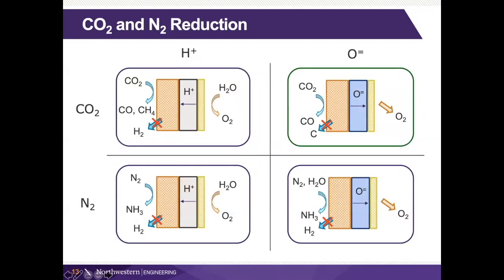And again, let me do the comparison with the oxygen ion conducting system. In the case of the proton conducting system, you bring in water, the protons come across and you react CO2. Ideally you're going to make some mixture of CO and methane. And again, we don't want to have the hydrogen evolved here. As Tom alluded to, this hydrogen evolution is a very easy reaction. So it's actually quite hard to prevent this reaction from occurring.